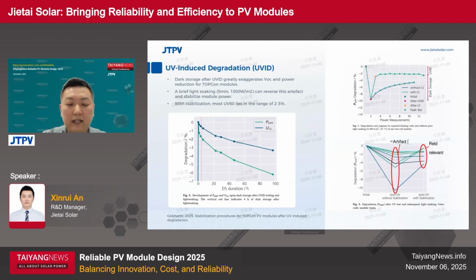It is shown that the dark storage after UV exposure can greatly exaggerate VOC and power reduction. A brief light soaking step can easily remove this artifact and is more representative of the real case scenario. But noticeably, even after light soaking, further dark storage can still distort power measurement. Ideally, we need to measure the power immediately after the light soaking. Nonetheless, UV60 in the range of 2 to 3% is quite common for most of the TOPCon modules under investigation. So UVID is still a problem to be reckoned with, in our opinion.